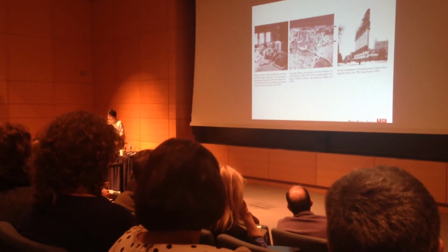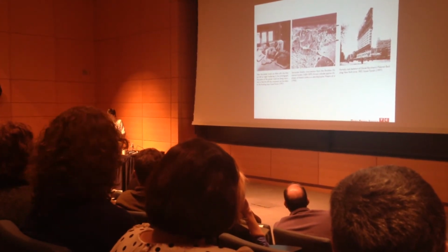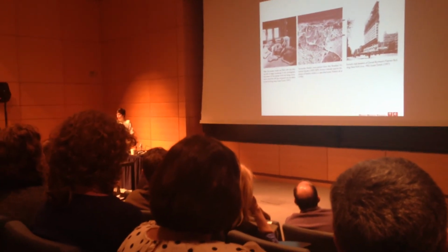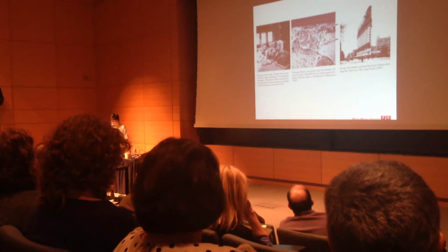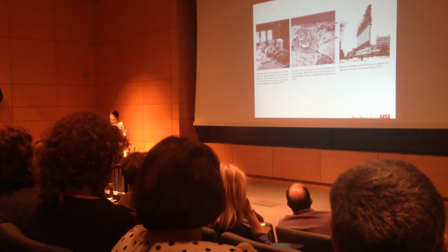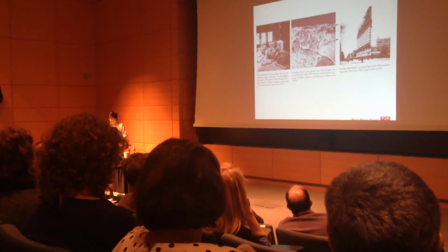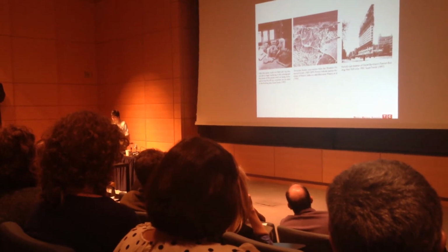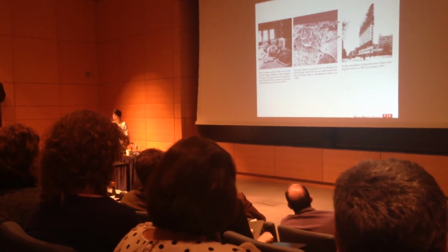For the purpose of our literature review, terracotta was defined based on the most common definitions used historically to describe the material: a structural or semi-structural molded clay product made of mixed clays. It's generally hand-pressed into an absorbent mold. The formation of the fire skin is related to the concentration of colloidal clay particles in the upper surface due to the suction of the plaster mold during drying. During firing, this zone then densifies during sintering, and becomes an important protective surface against the weathering of terracotta.